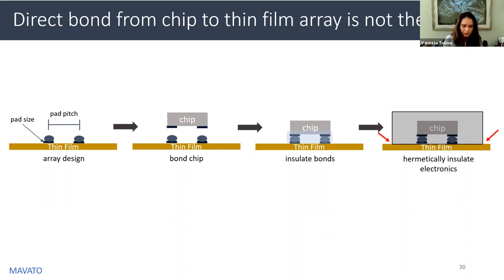So you eventually figure out the bonding process, and now you have to insulate the bonds. That's step three. And as with the other steps, when you're pushing boundaries, this step alone is its own project, so I won't spend too much time. And then lastly, you have to find a way to hermetically encapsulate the electronics from the environment. This is what's tricky with this design, because remember the other end of this thin film is the electrode array that's implanted into tissue, and fluid will travel up the cables and get to this interface that I pointed to in red. So without spending more time on this, I'll just leave it as this is a failure point for really long-term implants.